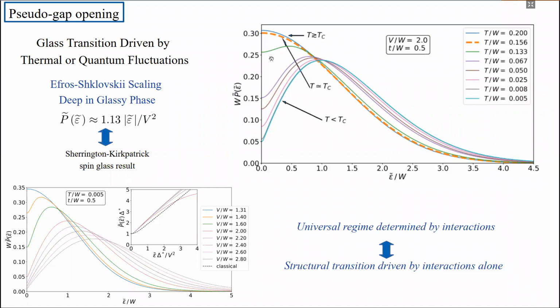So this is what one would expect naively. However, if we further decrease the temperature, then we see that the probabilities at small fields get suppressed, and there is this so-called pseudogap opening in this distribution P epsilon. Moreover, one can show that deep in the glassy phase, one finds an Efros-Shklovskii universal scaling for this field distribution function. So P epsilon at small fields is actually proportional to epsilon divided by V squared. This is exactly the same as the Sherrington-Kirkpatrick spin glass result.